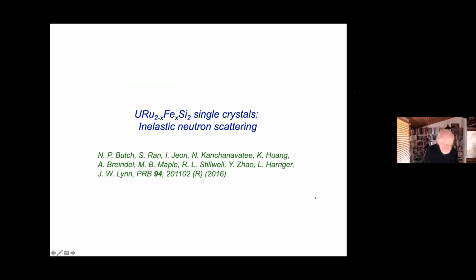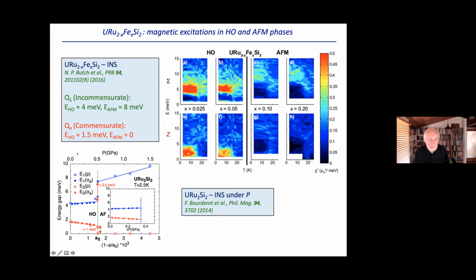Okay, so anyway, I see that I'm running out of time here, but let me now just come back to the inelastic neutron scattering. So this was work, again, done by Nick Butch and others. And so these are measurements of various iron concentrations, inelastic neutron scattering. So basically you see the incommensurate excitations, and the gap in the hidden order range is 4 meV, if you can remember back to the earlier slide. And then in the antiferromagnetic regime, it jumps up to about 8 meV.